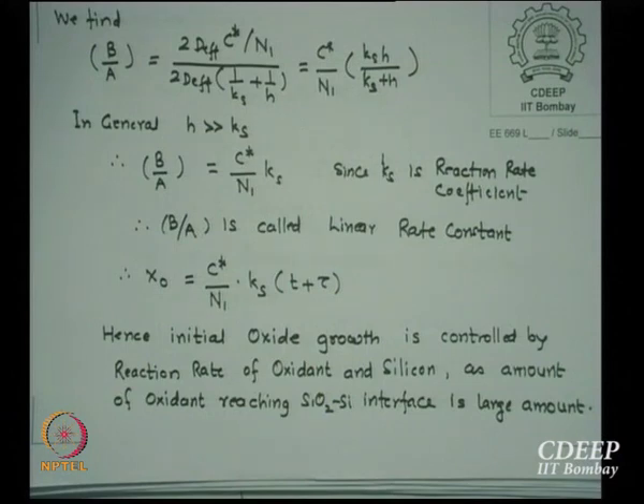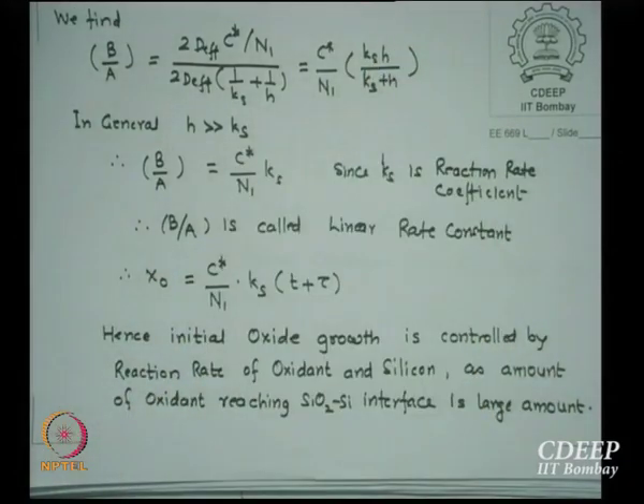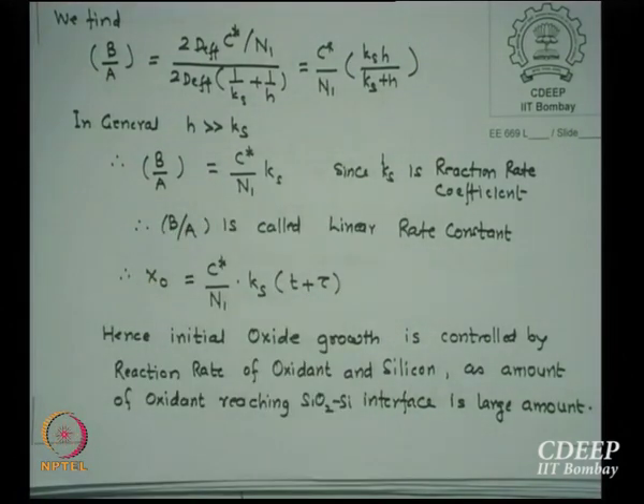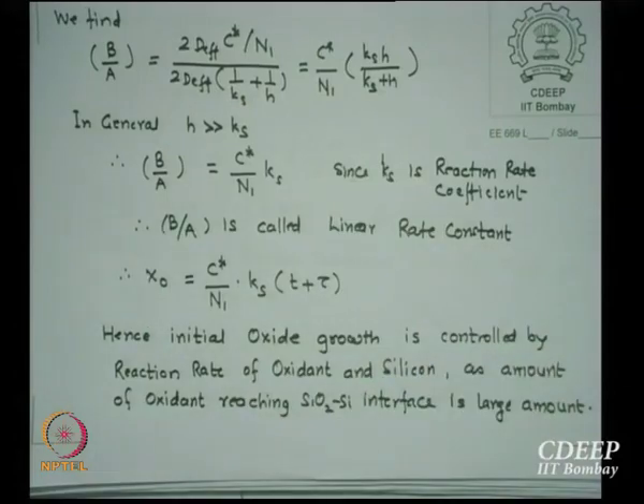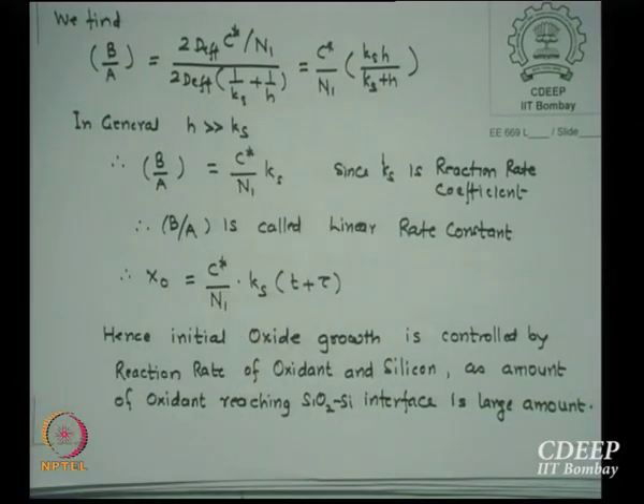So what happens in most normal cases? Which is it limited by, h or Ks? The smaller one limits it, the larger one doesn't limit it. I don't say this every time; in CVD we say it is mass transfer limited, but in this particular case we say h is much larger than Ks. So I can neglect h, 1 upon h goes away. So we get B by A equals C star by N1 into Ks. Is that okay? If h is larger than Ks, this can be neglected. 1 upon h is smaller compared to 1 upon Ks, and therefore we neglect h and we get C star upon N1 into Ks.